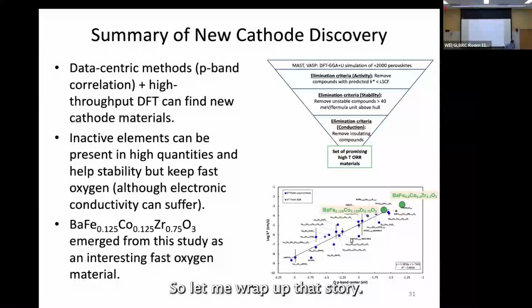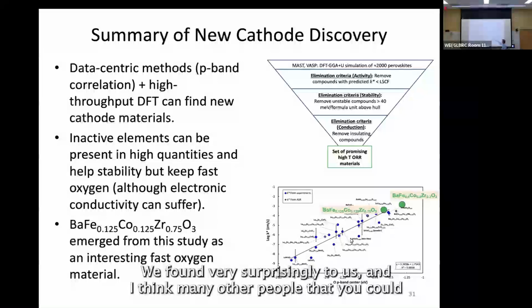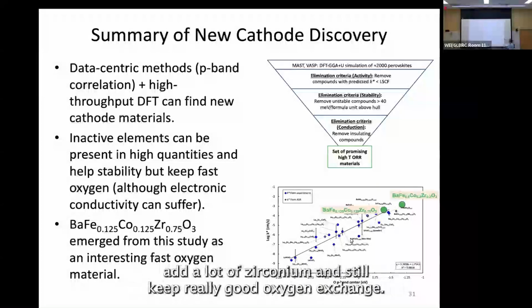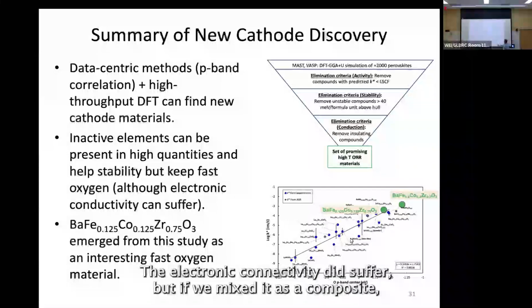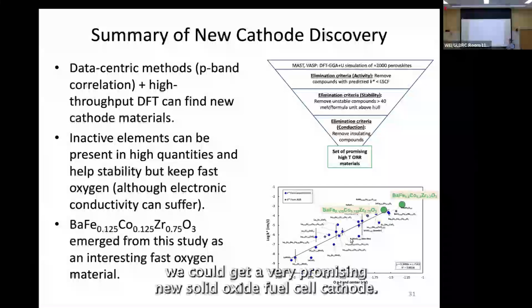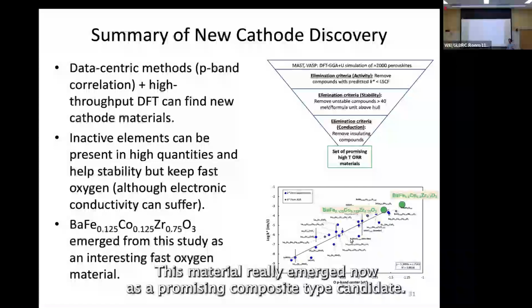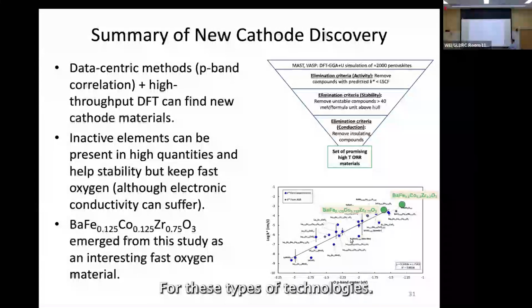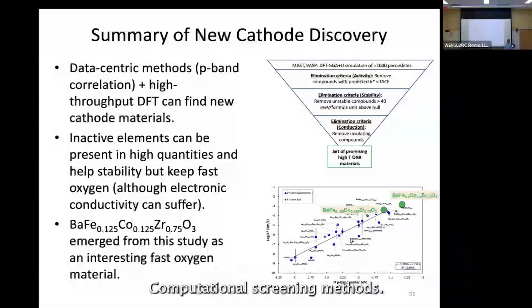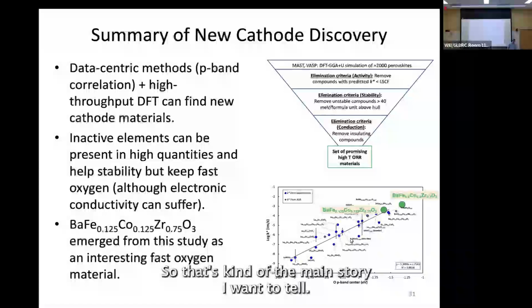Okay, so let me wrap up that story. We used these data-centric methods. We found, very surprisingly to us, and I think many other people, that you could add a lot of zirconium and still keep really good oxygen exchange. The electronic conductivity did suffer, but if we mixed it as a composite, we could get a very promising new solid oxide fuel cell cathode. And this material really emerged as a promising composite-type candidate for these technologies. And we were able to get there very quickly by using these computational screening methods. So that's the main story I want to tell.